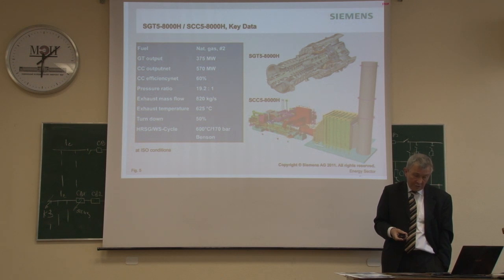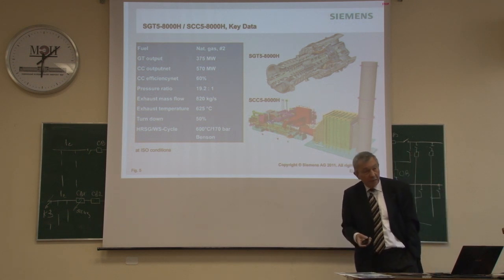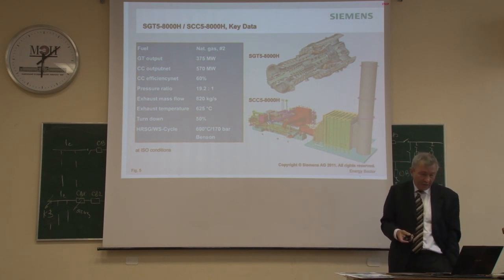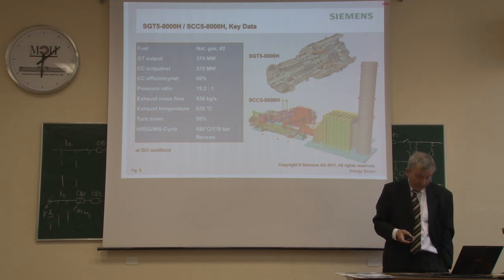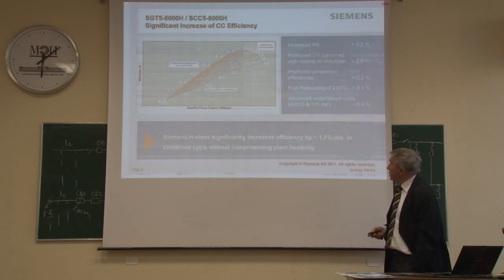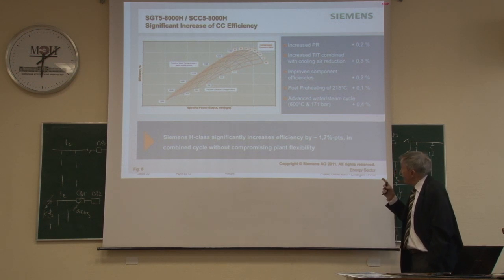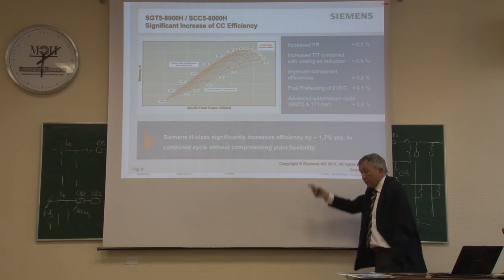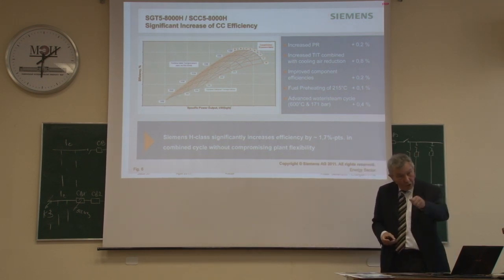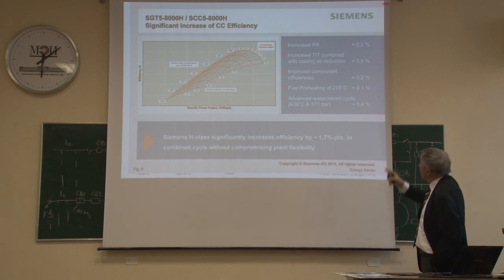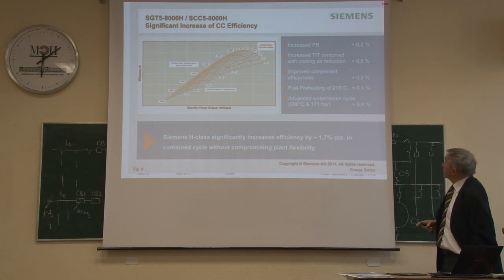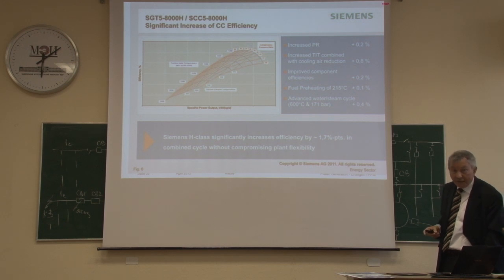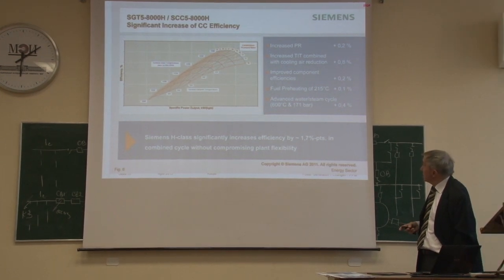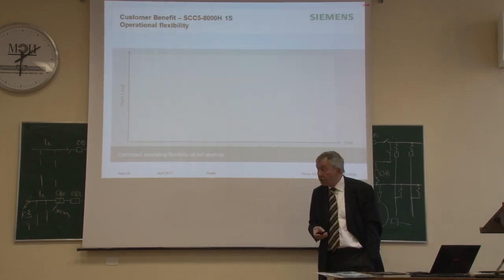The first engine was measured by the local TÜV, the licensing authority, to have an efficiency of 60.75%, and it runs rather well in many circumstances. This slide tells you where that improvement of about 1.7% came from. What were the knobs we turned for that purpose? We increased the pressure ratio, which gave about 0.2%. The main contribution, again, from raising the inlet temperature, we had an increase in component efficiency, better blades. We do preheat the fuel, and then also we have an advanced steam cycle, which results in those efficiencies above 60%.